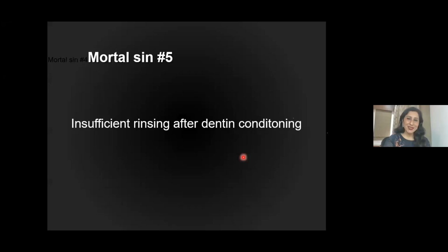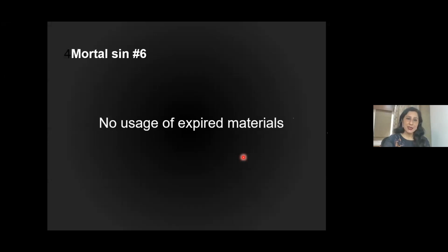Mortal sin number 4 is overdrying with a blast of air, or dentine dehydration. Please do not do that. Mortal sin number 5 is insufficient rinsing after dentine conditioning. That is, if you are using total etch technique, wherein you apply phosphoric acid gel both on enamel and dentine, then do remember to sufficiently rinse it so that all the phosphoric acid gel has been removed from the enamel as well as dentine. Number 6, no usage of expired material.